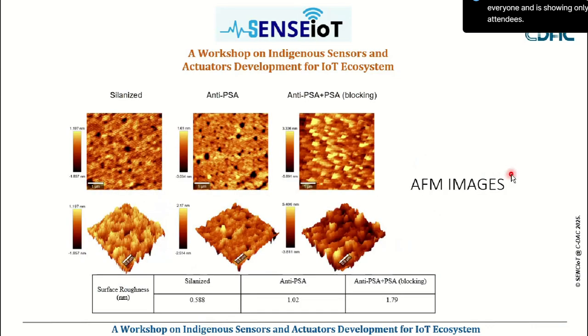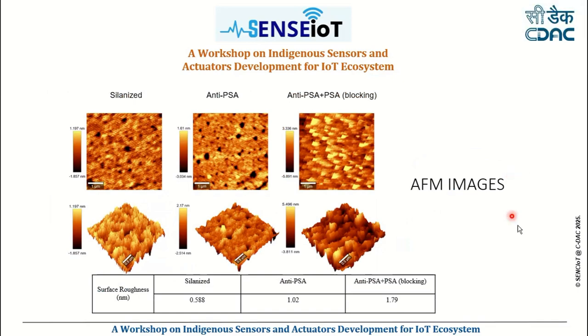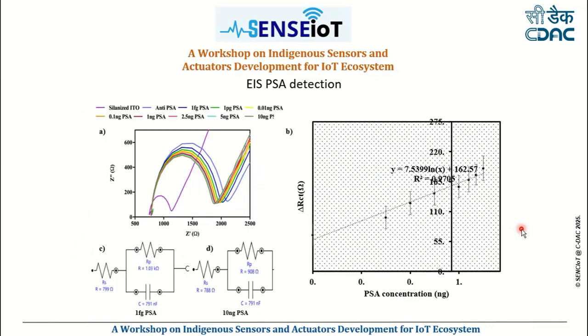So we also developed some sensors to detect biomarkers. For the biomarkers, here we have shown how layer by layer deposition was done. First the ITO surface was silanized, then the anti-PSA antibody was immobilized on top, and then prostate specific antigen binding to this anti-PSA antibody was obtained, and with the blocking, we can see that it can detect up to picomolar concentration.